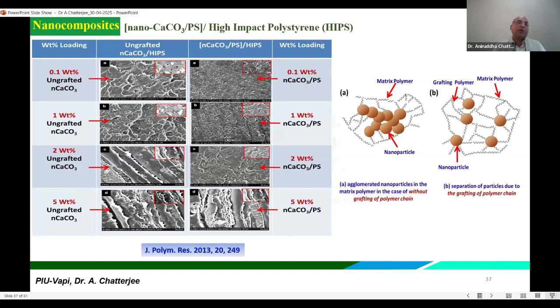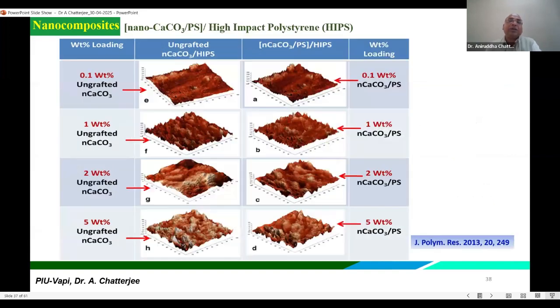Here you can see for ungrafted calcium carbonate nanoparticles, with 2% of loading, phase separation is observed. But with 2% of grafted nanoparticles loading, there is no phase separation. At 5% of loading, both show the same phase separation. It is a unique study I did during my studies.